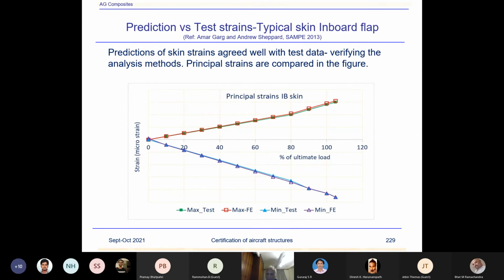One slide I've taken from our actual structured data, which is published. We could not show any real strain values here. We were not allowed to show any strain. So what you can see here is the test versus analysis. Prediction of skin strains agreed well with test data, verifying the analysis methods. The requirement was very stringent, matching the strains of the test data to the analysis within plus minus 5%, which is not easy, let me tell you.